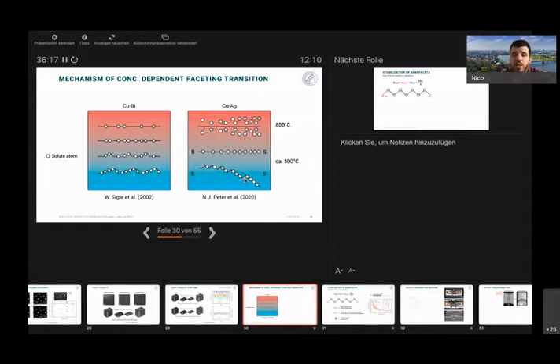But because of that, you need to introduce also a second segment, which is this asymmetric segment. And this one is constant in size. So it is more or less a kinetic barrier, what we believe, that defects that run along the boundary to form these silver decorated segments cannot move further. And the result of this is basically the more silver we have, the longer and higher frequency of segments we have, but the less silver there is, the lower it is, and the less frequent they come. So this is why we have this decrease in length, and therefore inducing this curvature to the boundary. So we don't think it's, for example, grain boundary induced migration.